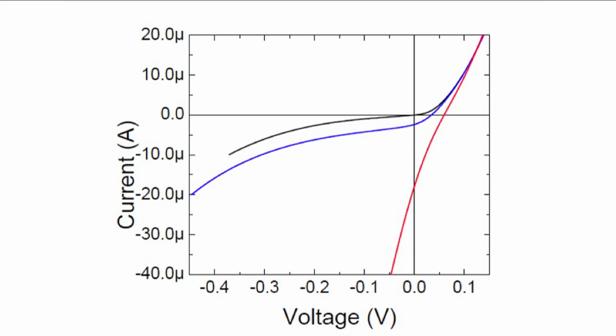This is the IV curve of such a detector. The black line corresponds to the detector cold, so it's inside a cryostat, but the shield inside the cryostat is closed. So it's surrounded by only cold radiation, and so there's very few background photons coming onto the detector. The shield is open, so now 300 Kelvin radiation can just come in and excite the detector. And so that means that this detector sees background radiation.